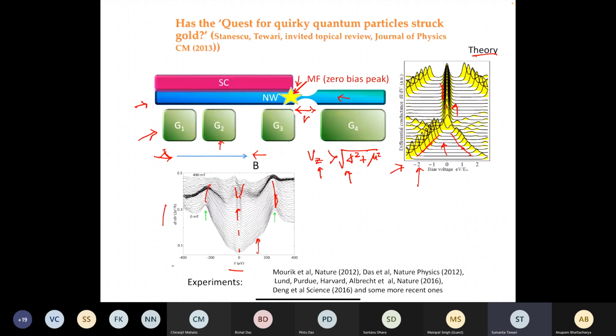Typically, if you think about a conventional d-wave superconductor like the high Tcs, if you do tunneling conductance near the edges, it is not unusual to see a zero bias peak. So zero bias peaks are not that uncommon. However, if you tune different parameters, let's say you apply a magnetic field, those zero bias peaks quickly split, because in a high Tc superconductor you have up spin and down spin. So the zero bias peaks split essentially because of the spin splitting. One peak comes from one spin, the other peak comes from the other spin, and they split as you increase the magnetic field. But here, the zero bias peak is very stable, at least over a range in magnetic field. So that was pretty startling.